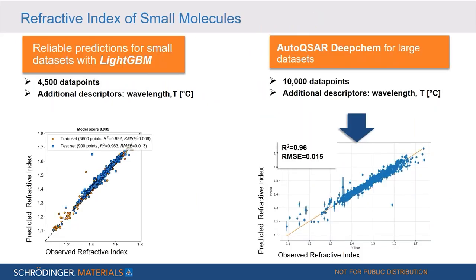And this example shows how the refractive index for small molecules can be predicted for large and small data sets. If we wanted to compute the refractive index for small molecules using physics-based simulations, we would first need to perform quantum chemical calculations, for instance, density functional theory, to obtain the polarizability, and then atomistic simulations of the condensed phase to get the system's density. And in order to avoid doing these atomistic simulations repeatedly all over again, whenever we have a new compound we would like to investigate, it would be good to use machine learning for the prediction of the refractive index.